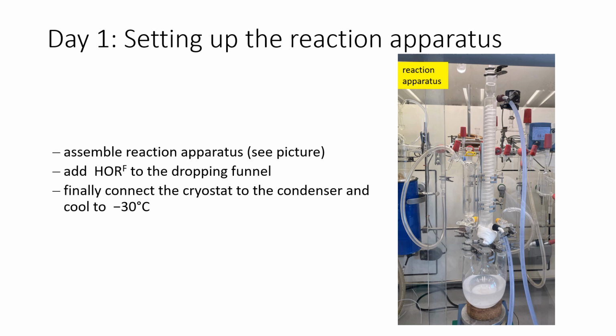In the next step, we assemble the reaction apparatus. This is shown in this picture here. Under a stream of argon, we attach the dropping funnel to the reaction apparatus as well as the condenser. Then we add the perfluorinated alcohol to the dropping funnel. Finally, we attach the cryostat and cool our condenser to -30 or -20 degrees. This is important to ensure that none of the alcohol is lost during the evolution of dihydrogen in the reaction.